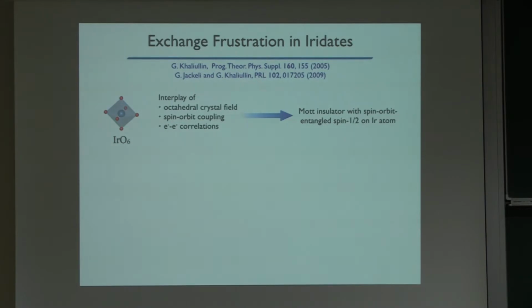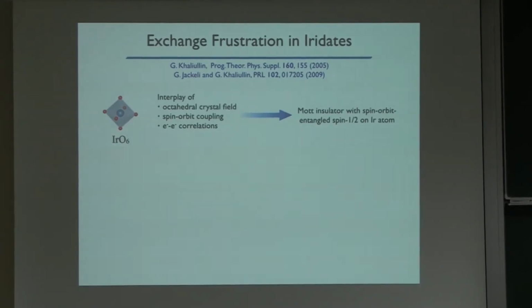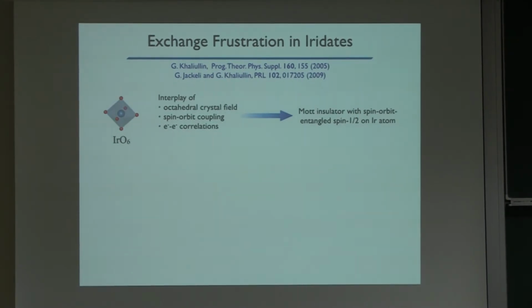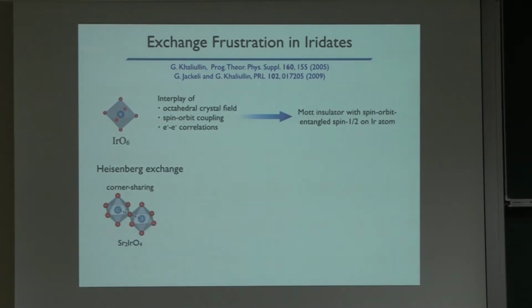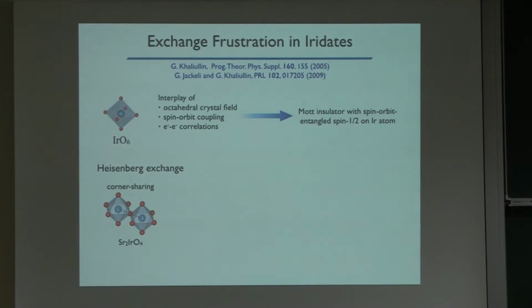So at the end of the day, what you get when all these conspire is you get a Mott insulator, which has an effective spin 1/2 degree of freedom, but it's not your pure spin, it's spin orbit entangled. So this spin knows about direction. So this spin really can have a direction-dependent interaction. So what interaction you do have depends a lot on how these octahedras are arranged with respect to each other. So one way of arranging them is this corner sharing arrangement. So you have an iridium atom here, another iridium atom here, so these are the magnetic sites.